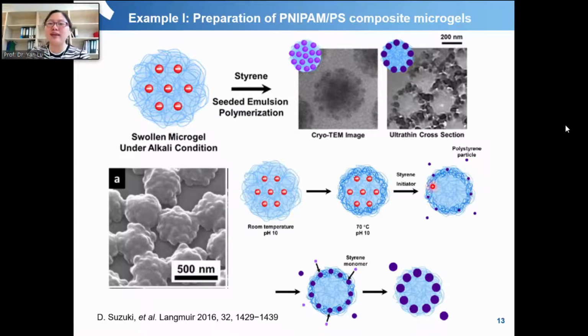And when they have a more hydrophilic inside and the shell around is hydrophobic at high temperature, that's why the polystyrene particle will prefer to immobilize into this hydrophobic layer. And there you will have a first nucleation of the polystyrene, and then the styrene monomer will swell your primary polystyrene particles and then grow there to form the final polystyrene particles.